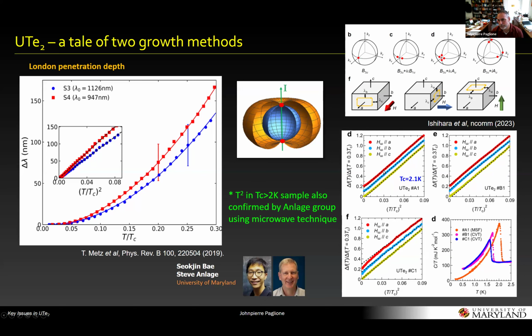the Shibauchi group measured penetration depth with their coils pointed in all three crystallographic directions, to apply field in three different directions. And they see T squared in all directions. So this drove them to conclude that there should be some component of a point node in all directions, which would mean it's inconsistent with a single point node or single pair of point nodes, for instance, in this B3U structure shown here. So this conclusion was consistent with a multi-component order.